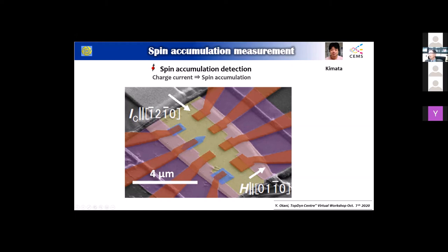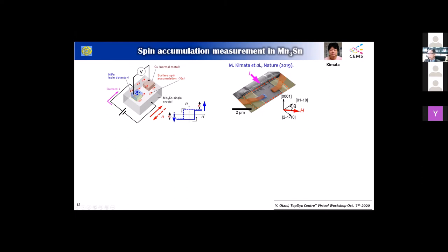The standard method uses a pair of electrodes — one side connected to a ferromagnet and the other side a non-magnetic copper — aligned perfectly perpendicular to the current direction, so that the chemical potential can be detected by the ferromagnet. We measured the voltage potential between the ferromagnet and the non-magnetic copper. If we switch the magnetization direction, we can expect hysteretic behavior, which is exactly the proof that we have spin accumulation on the surface.